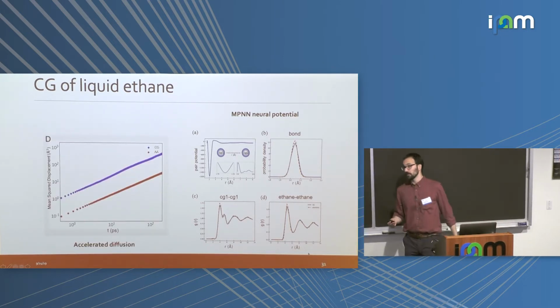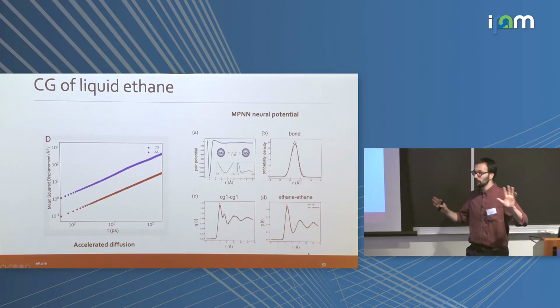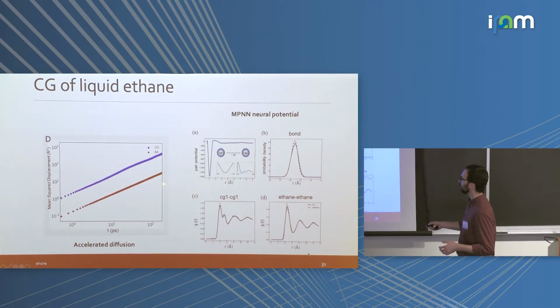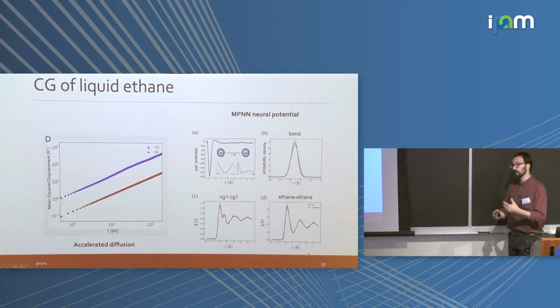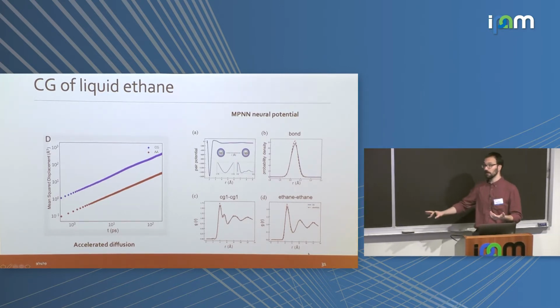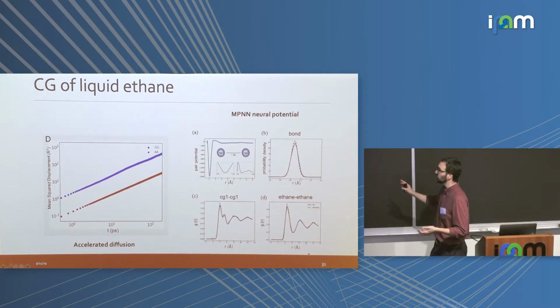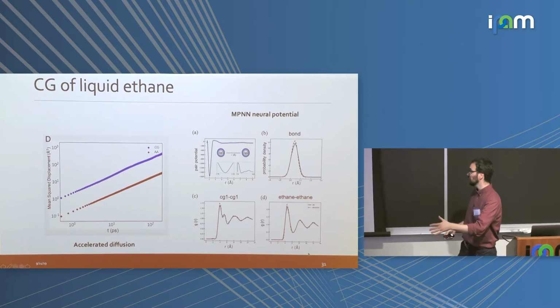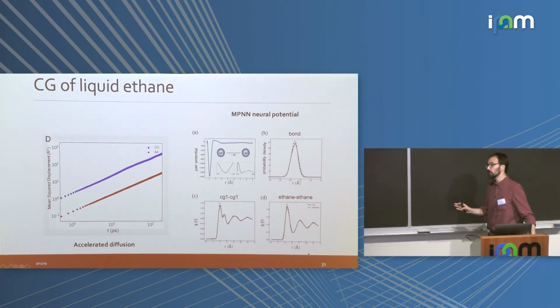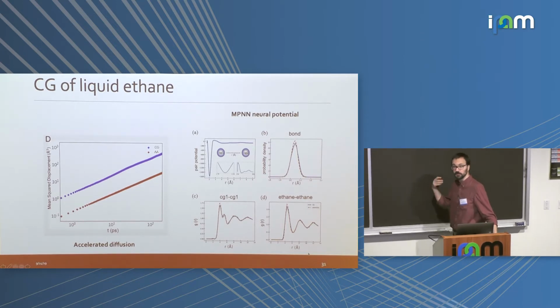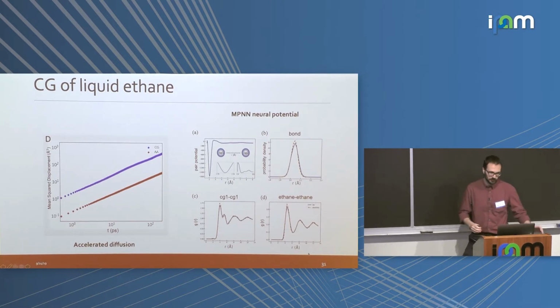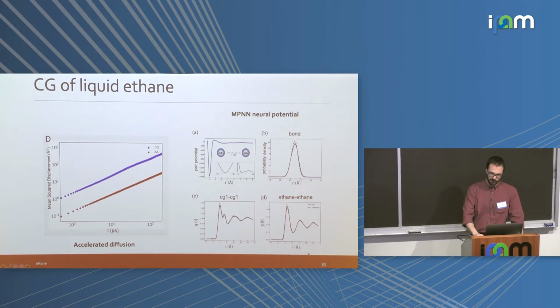Kinetics, what happens to kinetics? Well, that was never in the works. We never tried to make this work for kinetics, and what happens is what always happens in coarse-graining, very often, that the kinetics suddenly became much faster. We've taken a lot of modes out. There was a lot of friction. We haven't put it back into the generalized Langevin equation, so we're running regular dynamics, so they run much, much faster, which is not a huge issue because that's not what we were trying to do anyway. We're trying to accelerate dynamics, so the fact that we can attain the right structure faster is not a huge issue, at least if we're just interested in a structure.